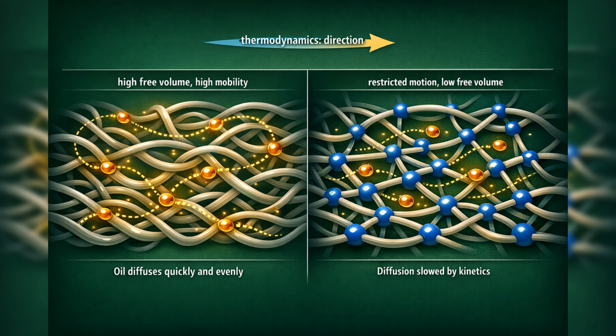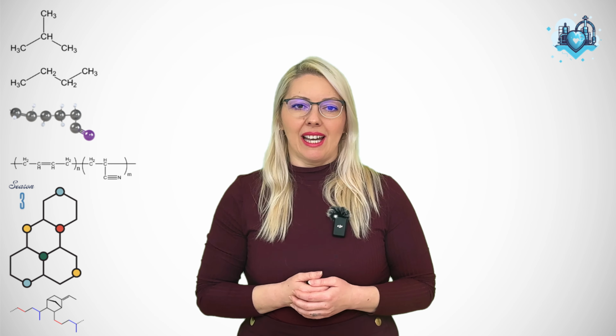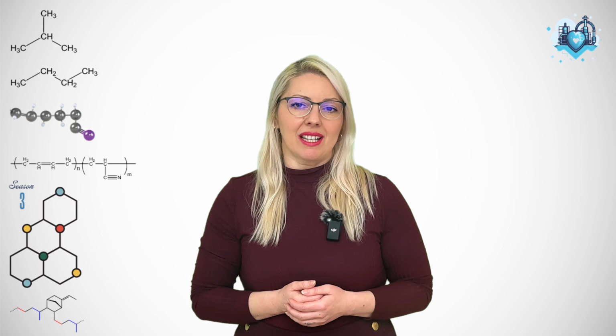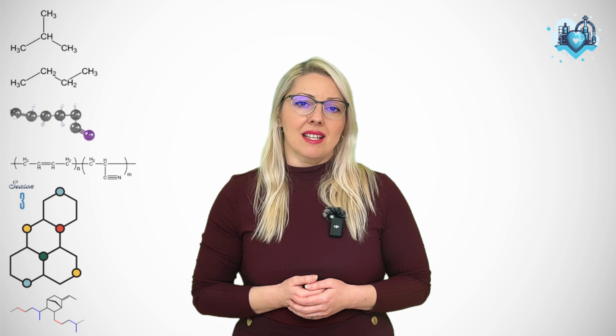This immediately explains the first big distinction: unvulcanized versus vulcanized rubber. In unvulcanized rubber, the polymer chains are long and only entangled, not chemically connected. They move freely under heat and shear. That creates a lot of free volume and transient pathways. Oil molecules diffuse quickly and redistribute easily. This is why oils added during mixing seem to disappear uniformly into the compound.